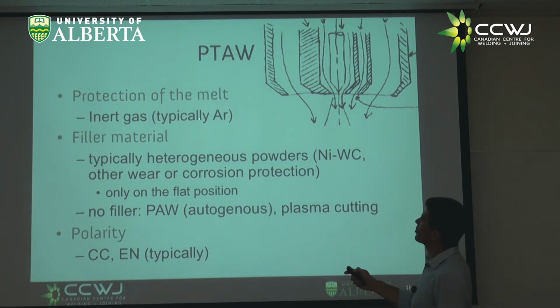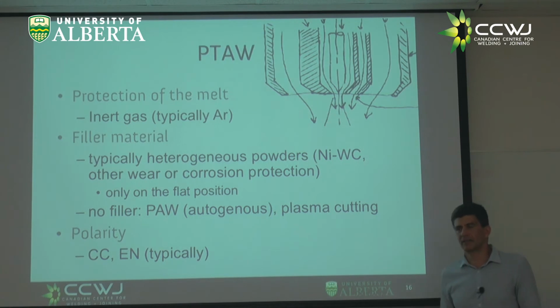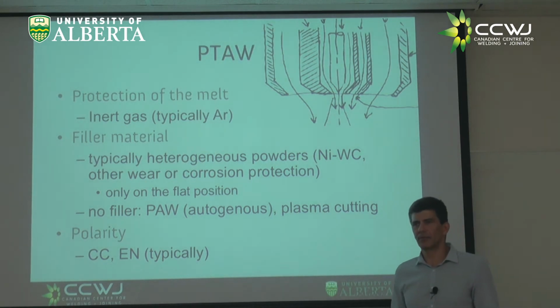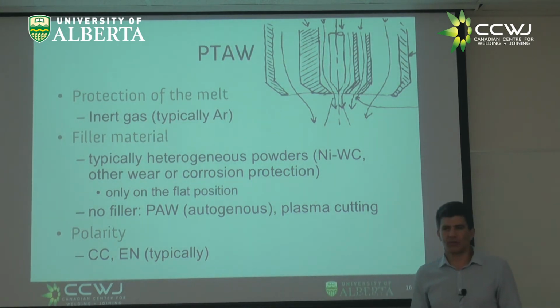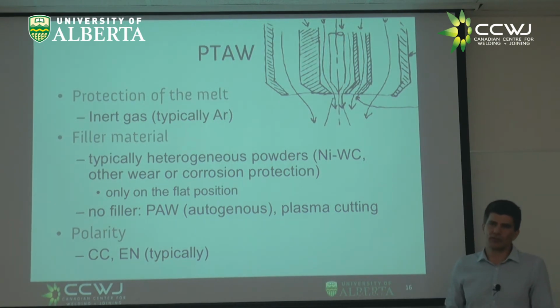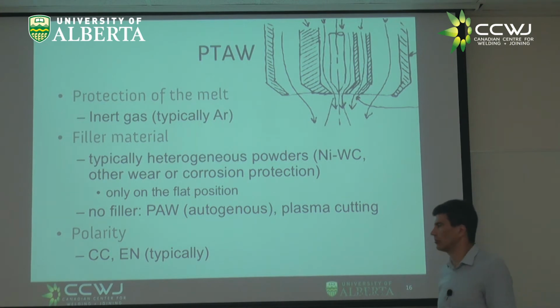Okay, protection of the melt, again, is a shielding gas, typically argon. Sometimes they put a little bit of hydrogen. We're going to see that hydrogen gives you a hot arc, and also is a reducing gas. On the other hand, hydrogen is typically very bad for steel. So if you're going to do it, you have to know what you're doing, so you don't get on the wrong side of things and end up with hydrogen cracking.